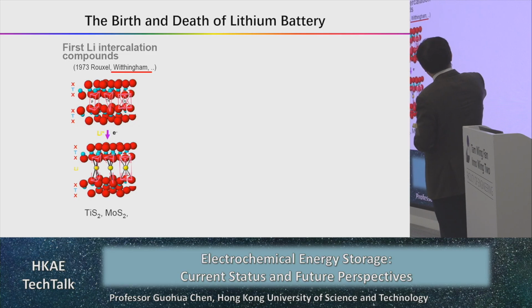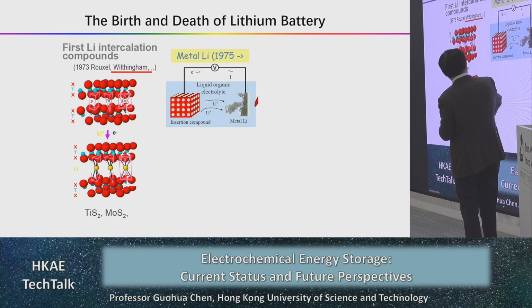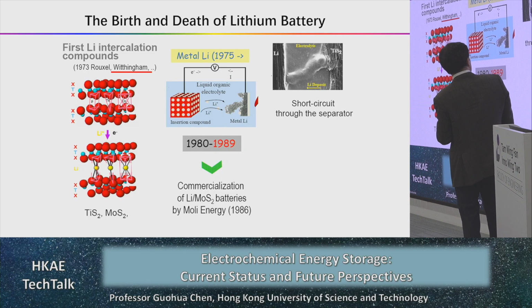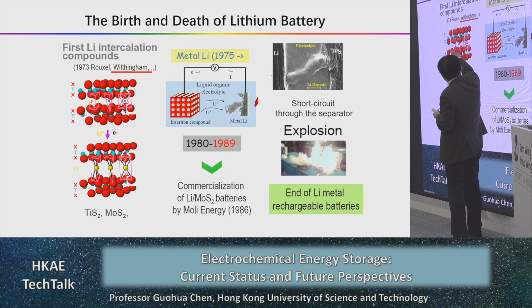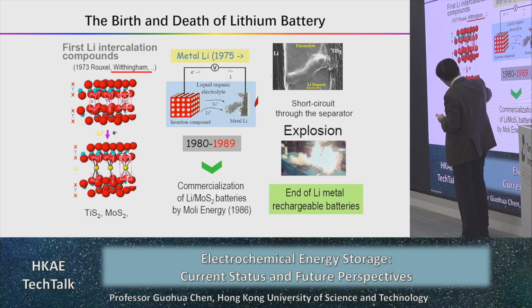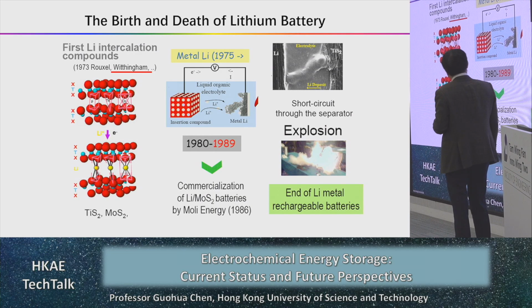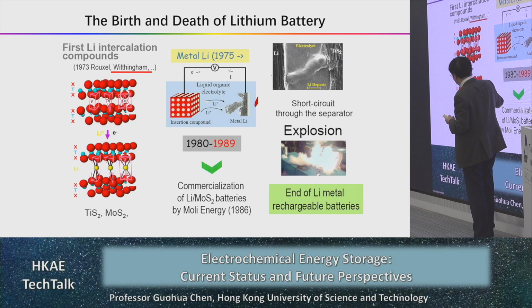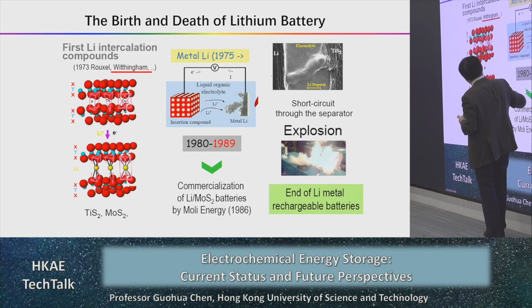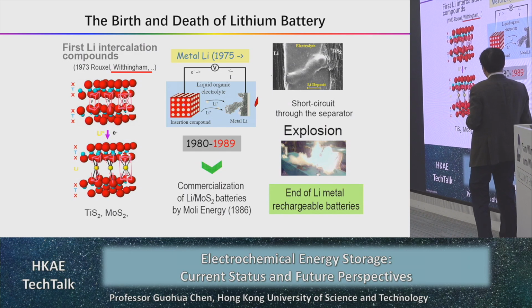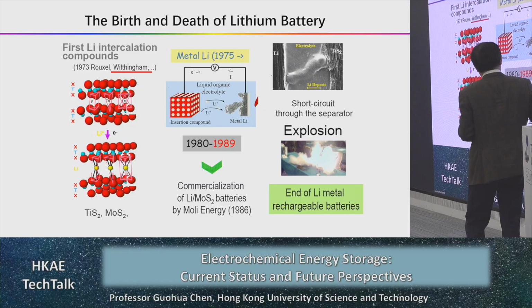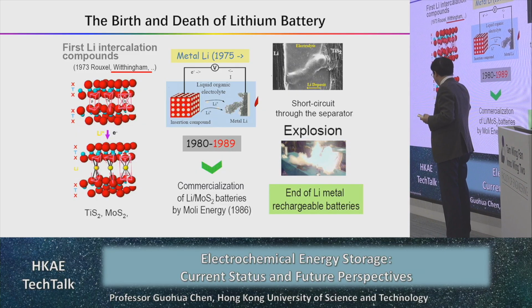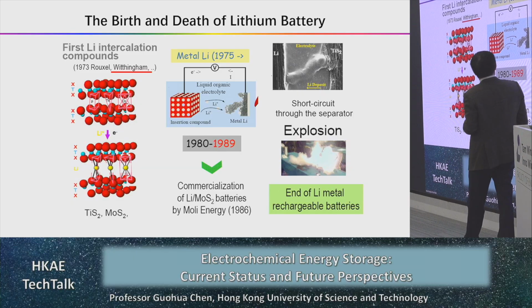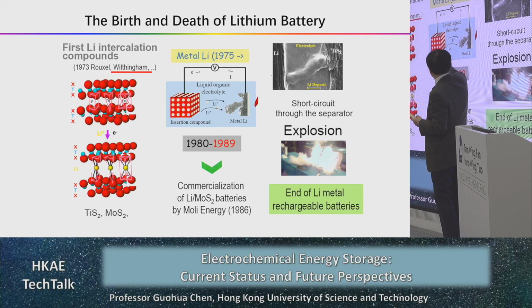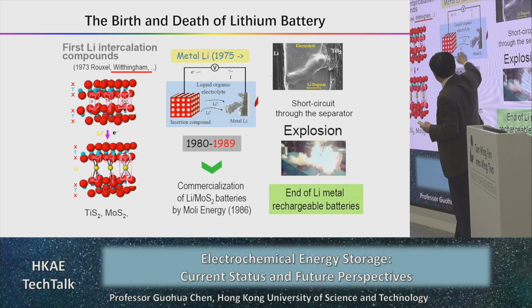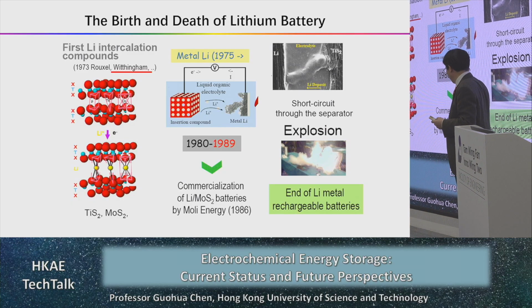And well, unsafe because we're talking about the birth and death of lithium batteries. So in the 70s, Whittingham found, using this chemical, titanium sulfide, the lithium can get in and out. We call it in and out between the layers in the space. And intercalation, we call it lithiation, delithiation, this kind of chemistry. And later on, this is made use together with the lithium metal as the anode, and that as cathode, and they made the commercial product.